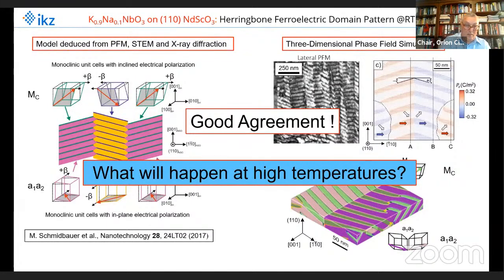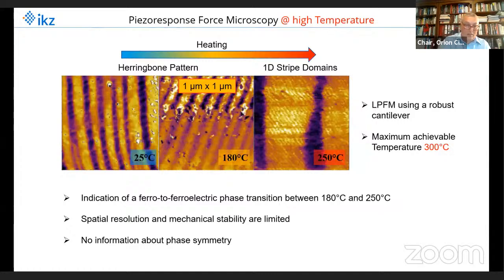So what will happen now at high temperatures? Let's heat up the sample and look at the PFM images. First I have to say, when you measure PFM at high temperatures, you have to use a rather robust cantilever, somehow reducing the experimental spatial resolution. So when you look at the left side, you do not see the herringbone pattern as well resolved as I have shown you already before, but this is the herringbone pattern we see here.